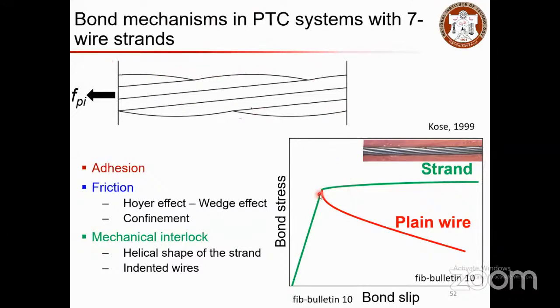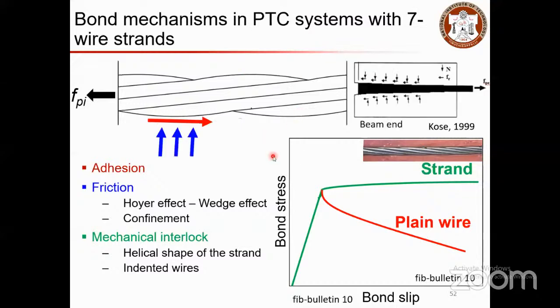The difference between the plain wire and strand is that when you have this strand, after the peak, the resistance to the slip will be enhanced better. In the friction, the effect will be due to the wedge action at the end. There will be a Hoyer effect that enhances the confinement, and you will have a mechanical interlock as well. So the helical shape of the strand would tend to increase the strength.